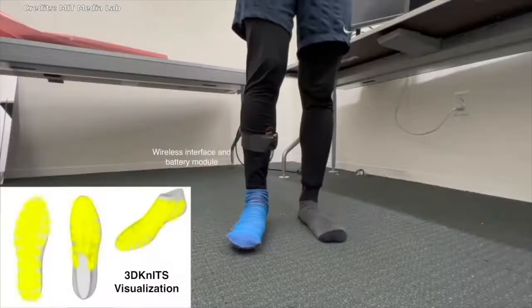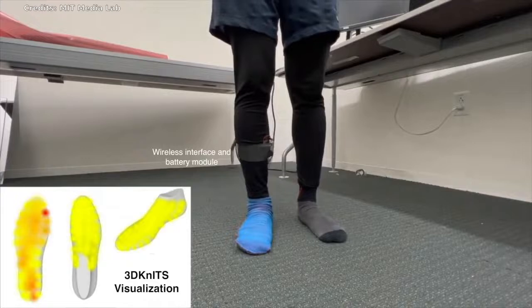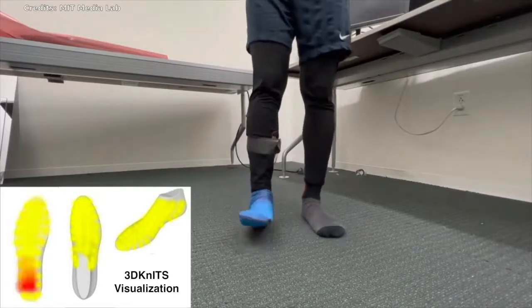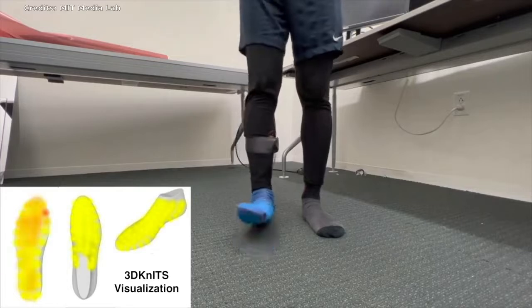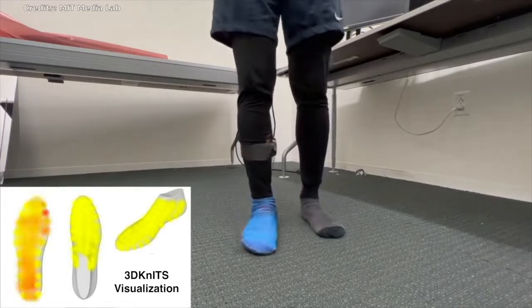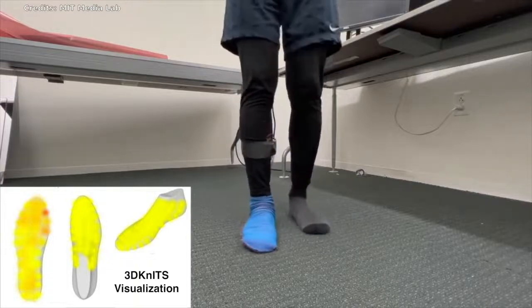He decided to try incorporating melting fibers and thermoforming into the smart textile fabrication process. The thermoforming readily solves the noise issue because it hardens the multi-layer textile into one layer by essentially squeezing and melting the whole fabric together, which improves the accuracy.